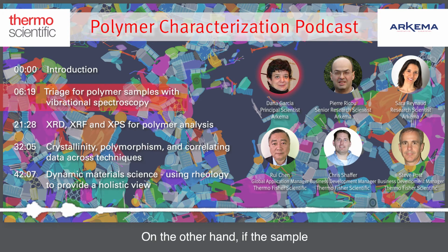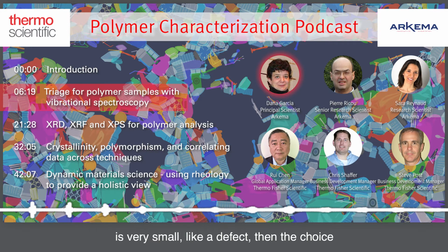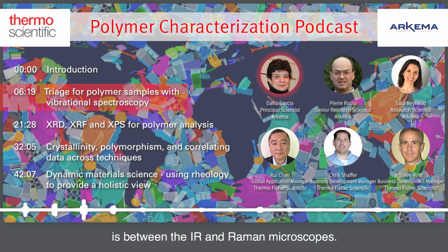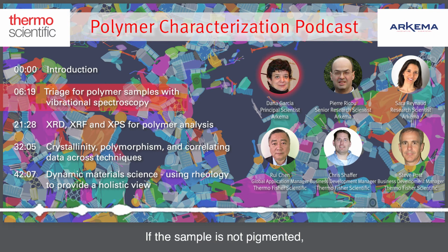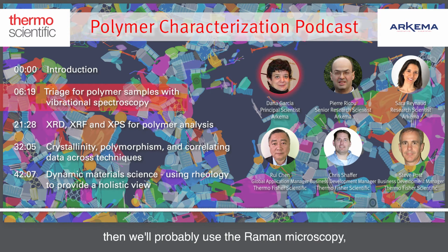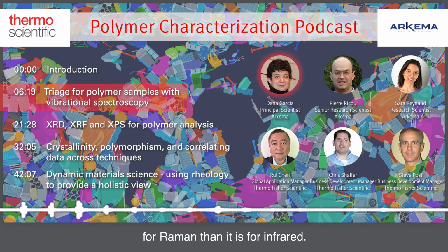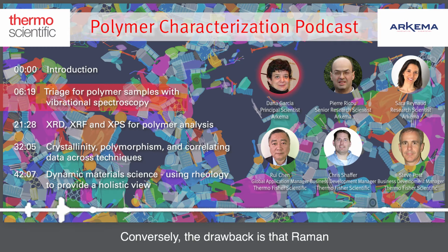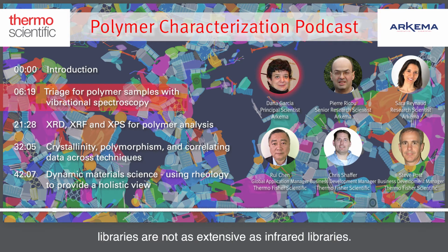On the other hand, if the sample is very small, like a defect, then the choice is between the IR and Raman microscopes. If the sample is not pigmented and we don't believe it will fluoresce, then we'll probably use Raman microscopy because it's easier to prep the sample for Raman than it is for infrared. And it's also faster. Conversely, the drawback is that Raman libraries are not as extensive as infrared libraries, so sometimes there's a challenge in identification. If the sample is pigmented or we believe it will fluoresce, then we use the infrared microscope.